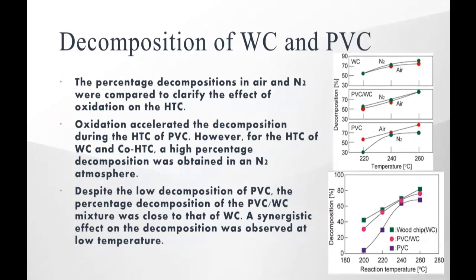Oxidation accelerated the decomposition during the hydrothermal carbonization of PVC. However, for the hydrothermal carbonization of wood chip and co-hydrothermal carbonization, a high percentage decomposition was obtained in a nitrogen atmosphere. Despite the low decomposition of PVC, the percentage decomposition of the PVC wood chip mixture was close to that of wood chip. A synergistic effect on the decomposition was observed at low temperature.